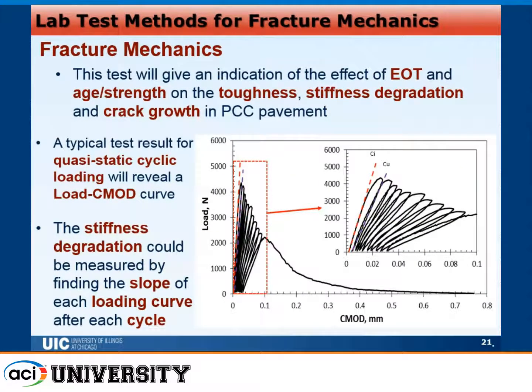This is a typical loading and unloading scenario for every sample. If you consider all the cases, we have with fibers and without fibers at 9 hours, 12 hours, 1 day, 2 days, 3 days, 7 days, 14, and 28 days, with and without fibers for all the mix designs.